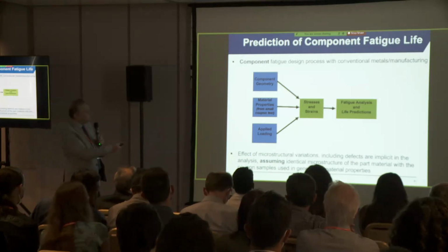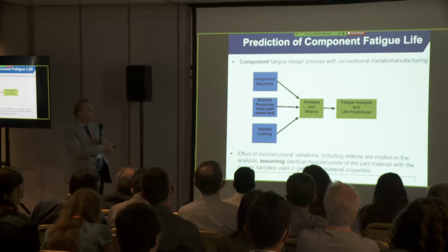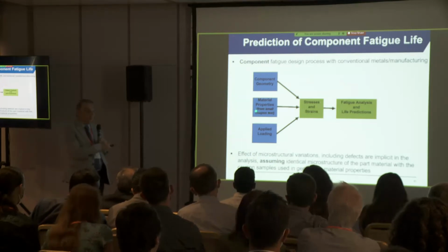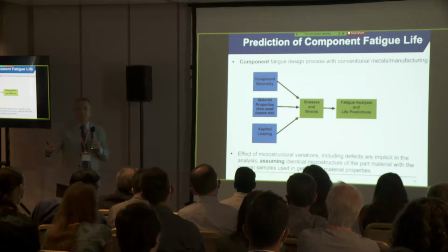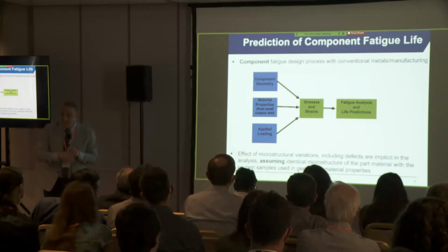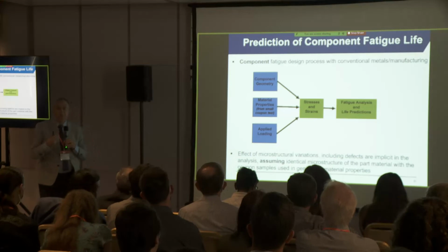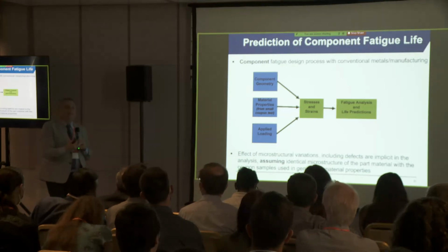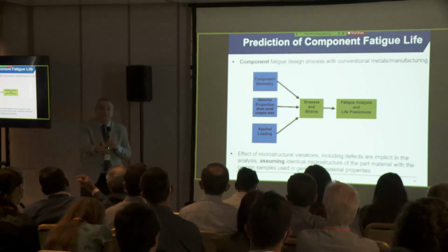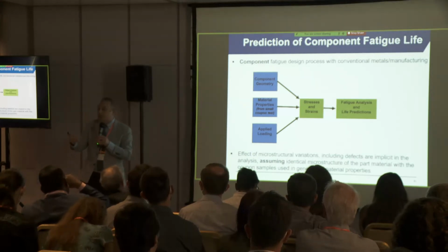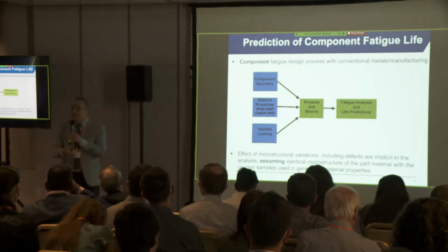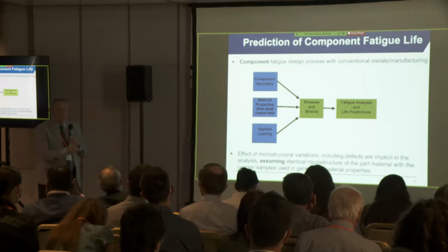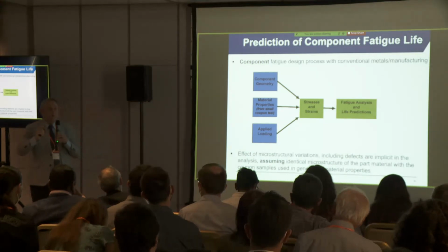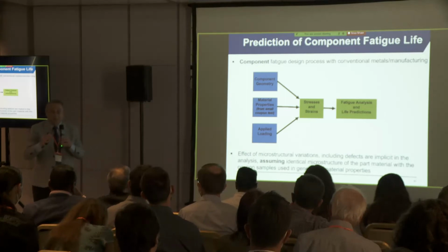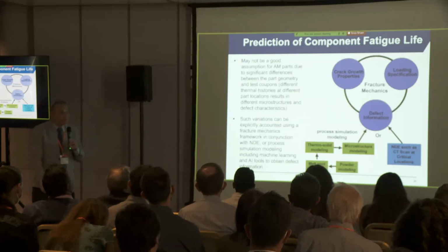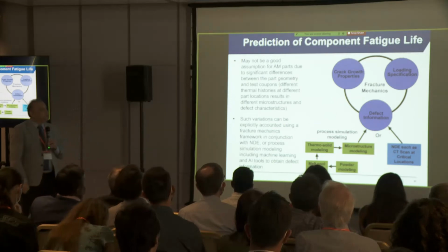Well, the big assumption here for conventional metal is that the material properties are representative of the material performance at the component level. Again, not so for additive manufacturing, because in an additive manufactured part, the population of defects, even the microstructure, are different throughout the part. So you cannot assume that the material property obtained from a coupon is representative of the additive manufactured part. Okay? So a much better approach, in my opinion, is using fracture mechanics.